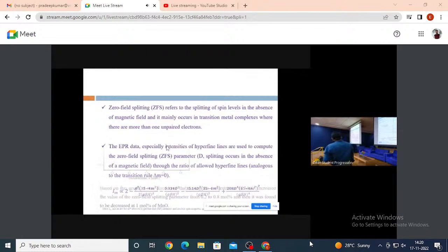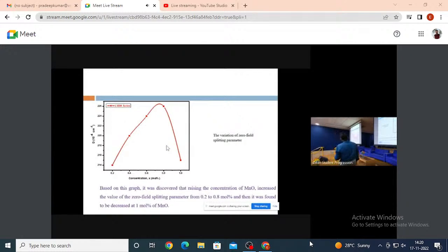Finally, based on the values, I have drawn the graph. Here also the zero field splitting parameters increase up to 0.8 mole percent of MnO. Later the zero field splitting parameter value is found to decrease.